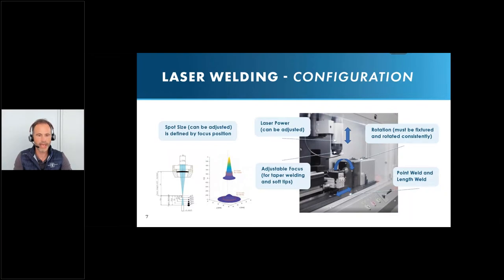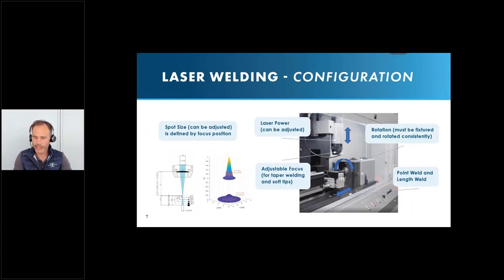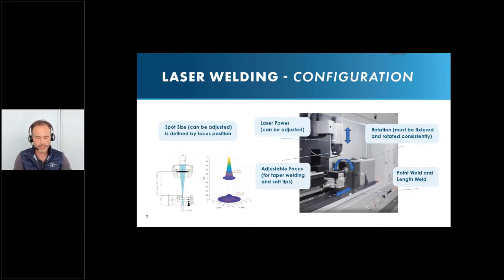Energy take-up and laser power: a good bond is an interplay between laser power, laser duration, laser travel speed, spot size, and rotation speed. The first three parameters define the overall energy take-up, the spot size defines the local energy density, and the rotation speed assures uniform heat distribution. To increase energy take-up, increase laser power, increase laser duration, or decrease laser travel speed. A good strategy is to start with a low energy take-up and work your way up. A medium rotation speed allows uniform heat distribution over the whole surface, achieved by tightly assembled product and a fitting straight mandrel.